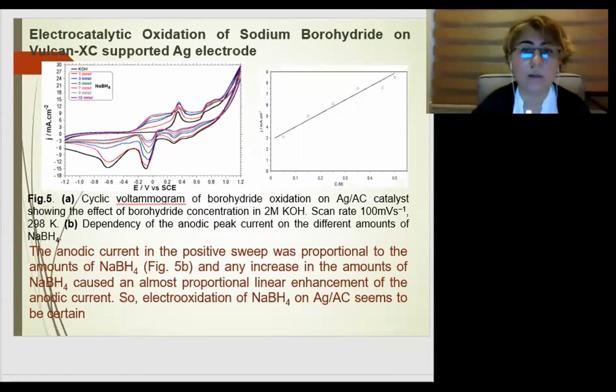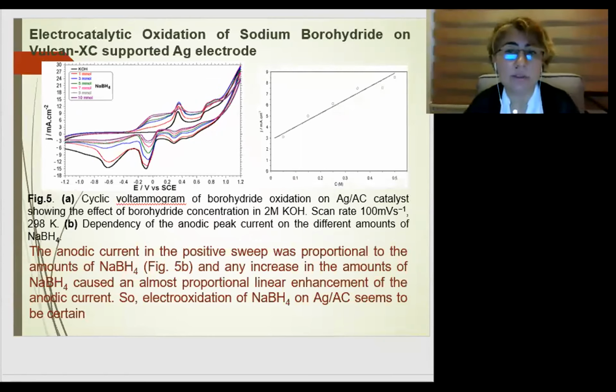and in figure 5, the anodic current in the positive sweep was proportional to the amount of sodium borohydride, and any increase in the amount of sodium borohydride caused an almost proportional linear enhancement of the anodic current. So electrooxidation of sodium borohydride on this catalyst seems to be certain.